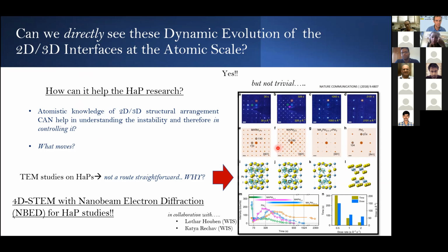Within an electron dose as low as 100 electrons per angstrom squared, the material starts to degrade and form some non-stoichiometric perovskite phases. Basically, the material that we wanted to study is not the same once we shine the electron beam on top of it.